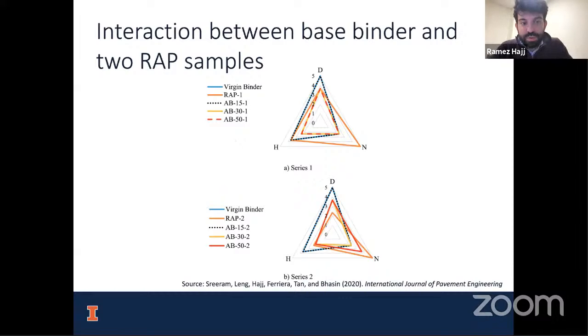Now, we can also look at the interaction between RAP and base binder. And what we see also is that when we start mixing in 3 different concentrations, 15% RAP, 30% RAP, and 50% RAP, we start to again see that the dispersion changes rapidly. So 15% is largely okay, has very similar behavior to the virgin binder in the case of 2 different RAPs. But as we start to add more and more, we start to see it become less dispersive.